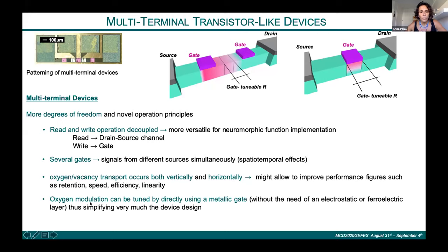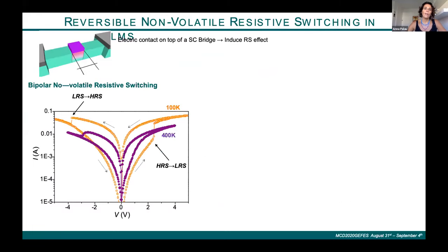And also, it's important to stress that in these systems, we can just use the metallic gate as a gate for inducing the switching effect, without the need of any electrostatic or ferroelectric layer, which would simplify very much the design of the system. Here I present an example of the switching performance of one of these devices with just one gate.